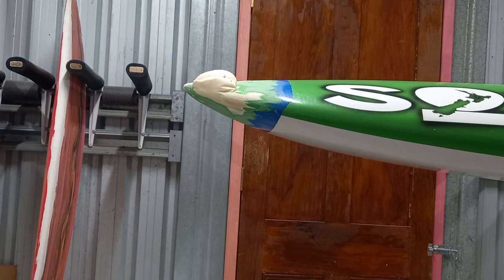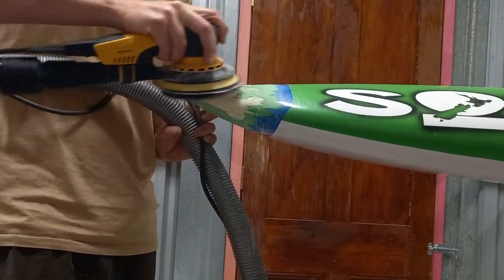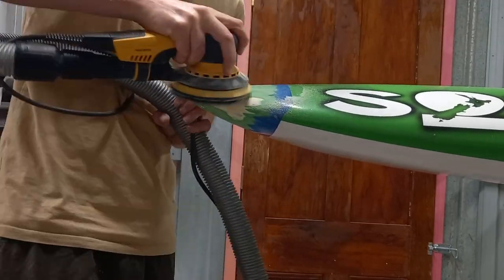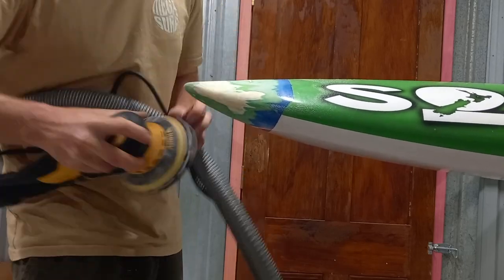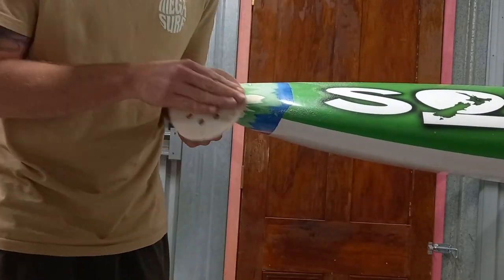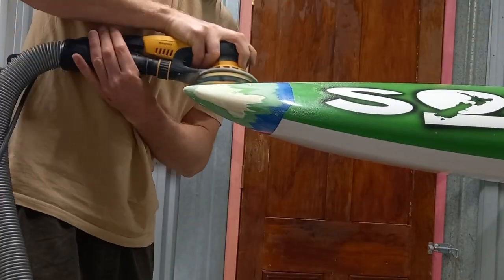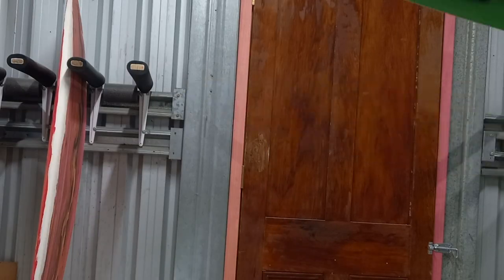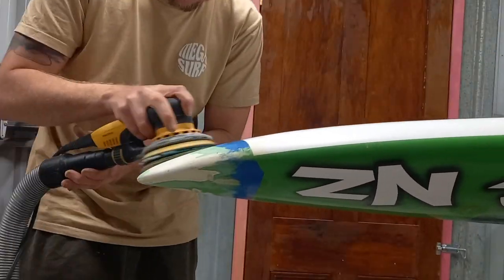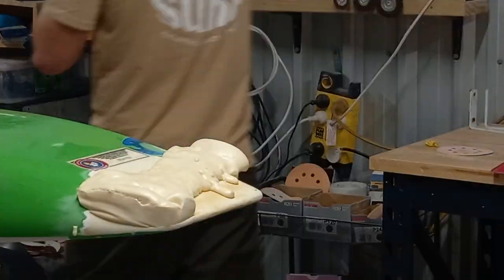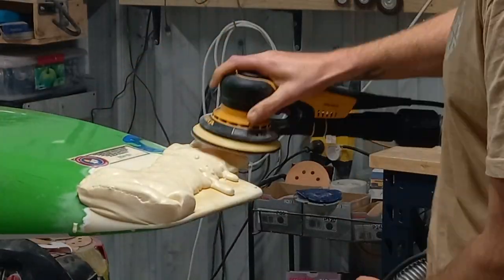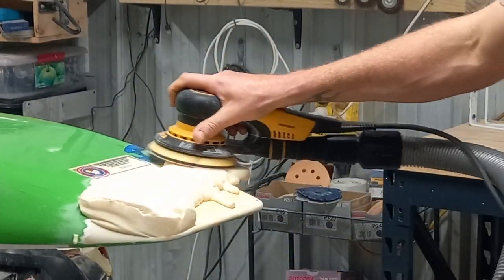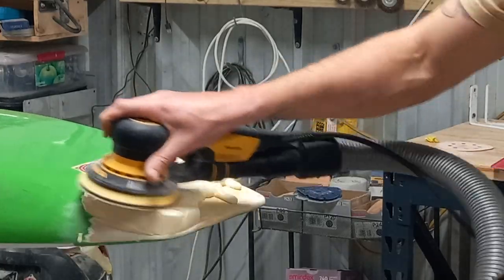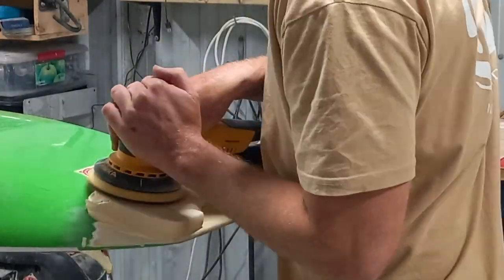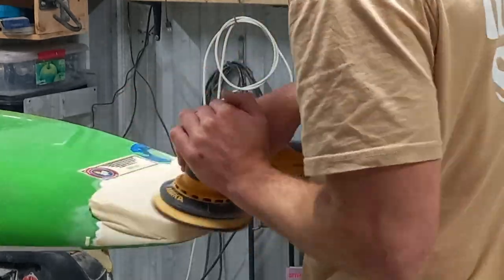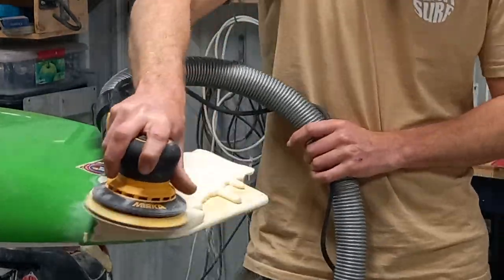So our favourite job, of course, we all know it's sanding. So just going to sand it down to shape as close as can. Can go a little bit lower if need, because there's probably going to be some small air bubbles in it. And that means we're going to give it a skim with a resin and microballoon mix next. Same deal with the tail. Obviously quite a lot of foam to be getting rid of, so I'm going a hard pad and some 80 grit to start off with. Once I get closer, I'll put the soft pad on and use 120 to kind of get it to shape.